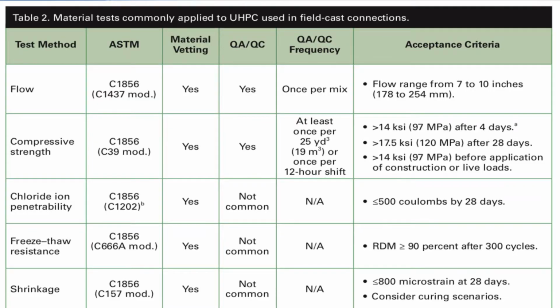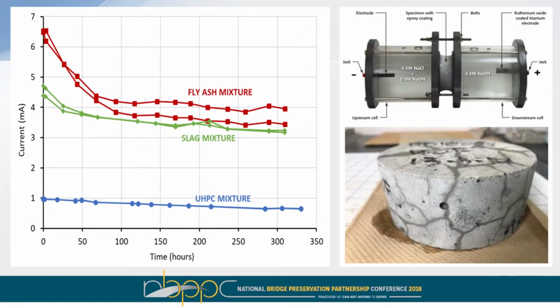General properties, we already touched on this, but everyone talks about compressive strength. But again, to Zach's point, I think that's really not the driving factor here. We're really looking at the impermeability and the durability of this technology. So just to give you a visual example, the top two lines are a more conventional high-performance concrete mix. And this is a test that measures the amount of current that can pass through a specimen. You can see a UHPC mixture versus a high-performance concrete mixture. Much, much lower current passing through, which is a representation of how impermeable the material is.